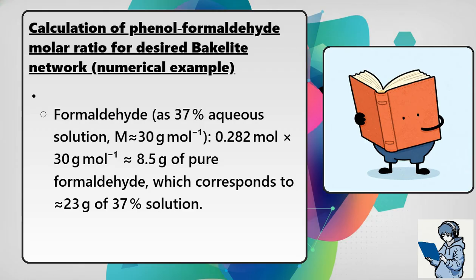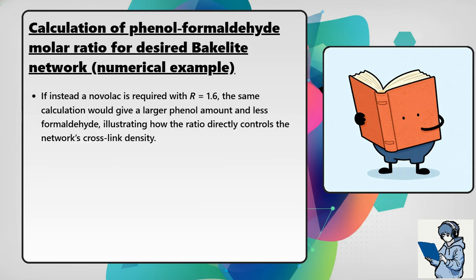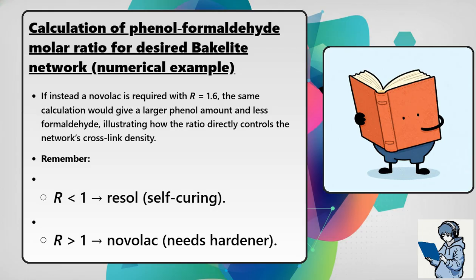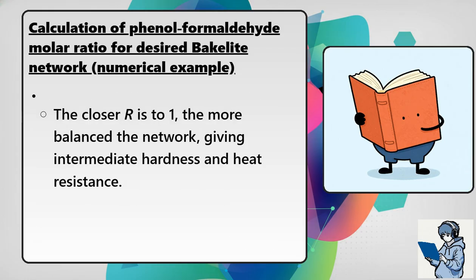0.282 moles times 30 grams per mole, approximately 8.5 grams of pure formaldehyde, which corresponds to approximately 23 grams of 37% solution. If instead a Novolac is required with R equals 1.6, the same calculation would give a larger phenol amount and less formaldehyde, illustrating how the ratio directly controls the network's cross-link density. Remember, R less than 1 yields Resol, self-curing. R greater than 1 yields Novolac, needs hardener. The closer R is to 1, the more balanced the network, giving intermediate hardness and heat resistance.